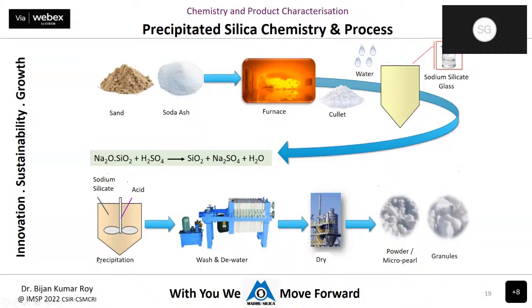So the first step is the reaction, the second step is the filtration, and the third step is the drying. In the first step, where the silica is precipitated out, it is in the tune of 8 to 10% only, or even 5 to 8% only, to be very precise. The rest is water and the byproduct sodium sulfate. After filtration, when the filter cake is formed, the water content is around 80%, only 20% is solid. And when we dry it, this water is driven off and we get the pure silica.